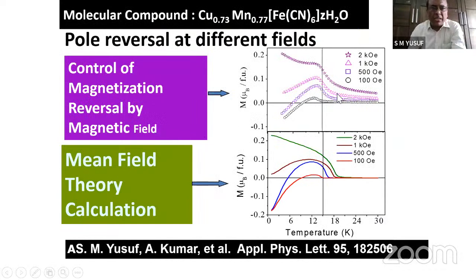We also extended this to find the effect of external magnetic field. As you increase the magnetic field, this magnetization reversal can be stopped and the magnetization remains positive, which is more conventional. This is again a mean field theory calculation under field. It also tells that.